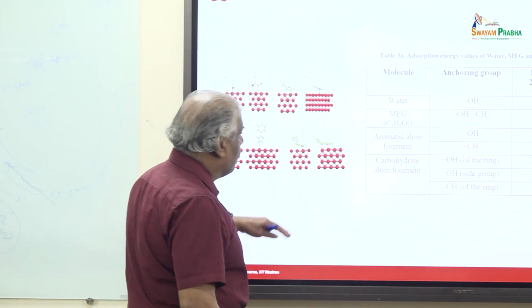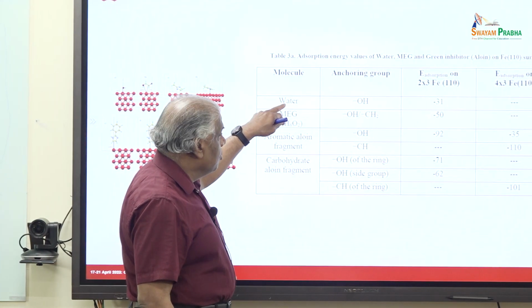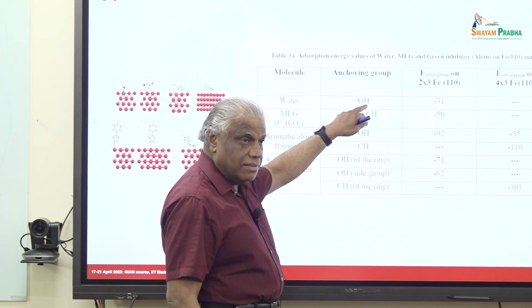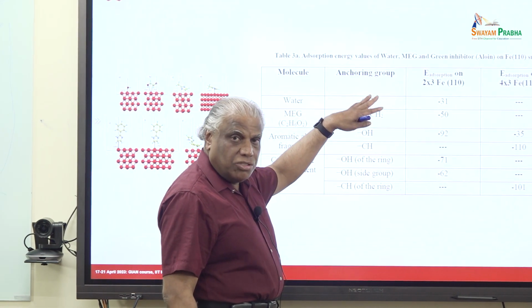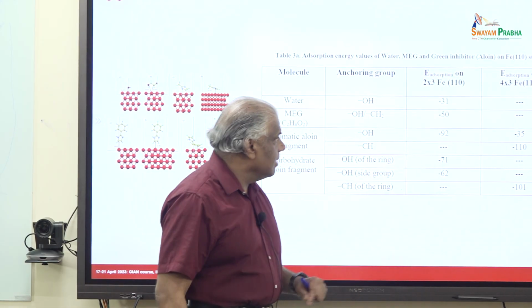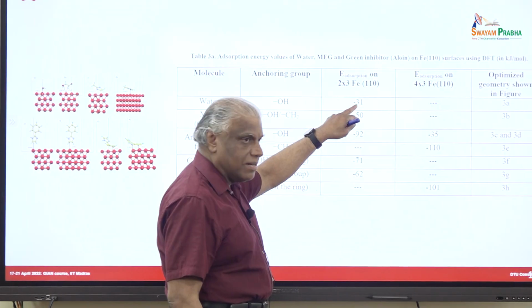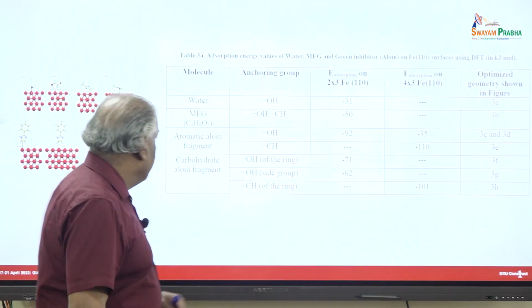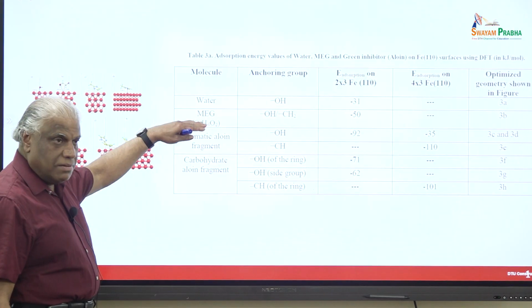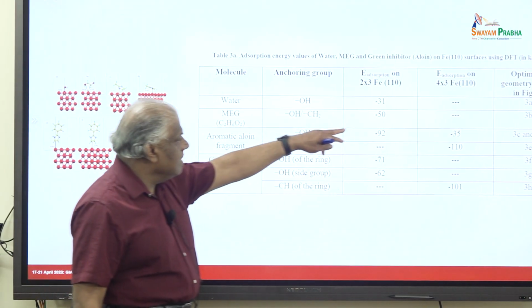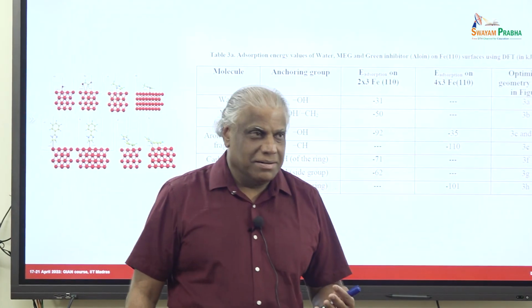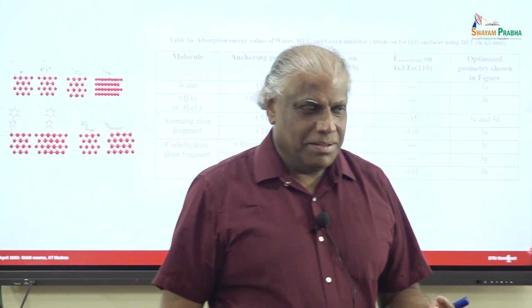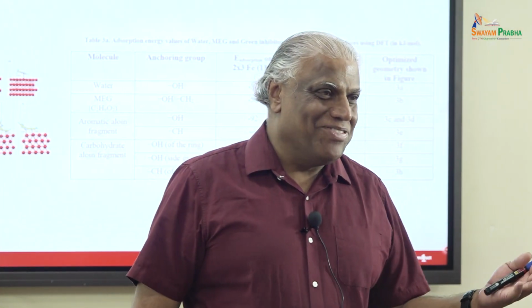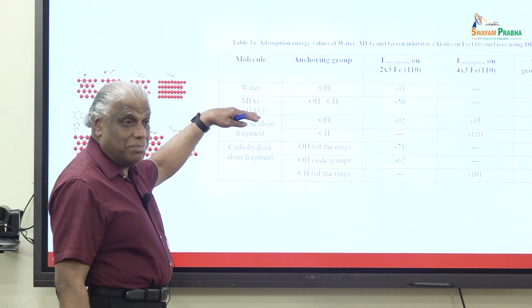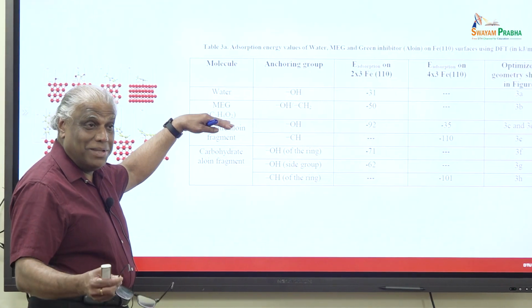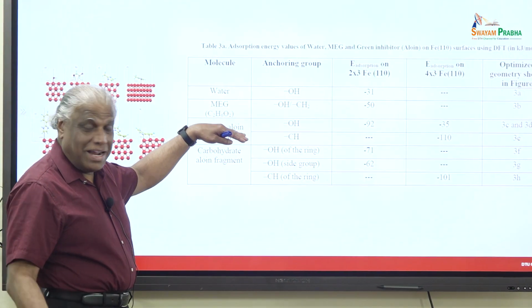How do we do that? For example, we also take water. You can see that water has an OH group, right? So we absorb water and find out the absorption energy. In this case, the absorption energy for water is -31. Then we take MEG, for example, and the absorption energy for MEG is -50. So which one is better? What we learned yesterday: more negative free energy means monoethylene glycol is better. So that's what it shows. Probably that's the reason monoethylene glycol works when they add it into the inhibitor.